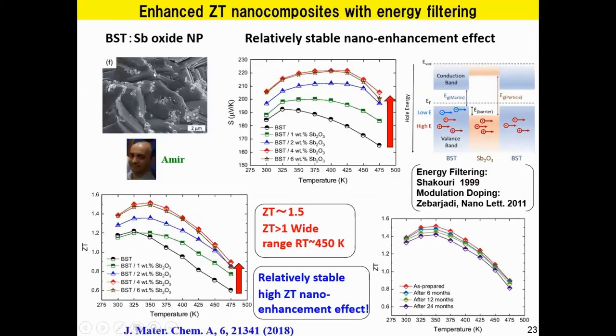Again, a former postdoc, Amir, put these nanoparticles of oxide in this bismuth telluride material to achieve very high performance, like 1.5. And the idea is basically that when you have these interfaces of different materials, you can have an energy barrier and only the high energy carriers go through. And the Seebeck is basically the entropy per electrical carrier, so it can boost up the Seebeck. So this was the idea, not by us, again, by an American professor. Of course, it's very important to effectively implement these principles, and we get this high ZT. So this was another nice result by boosting the Seebeck.